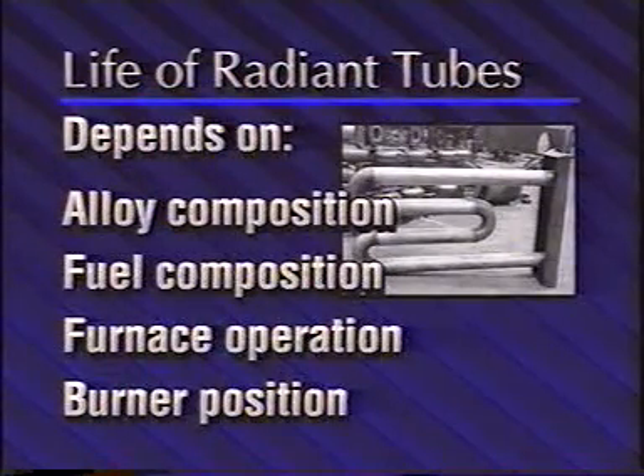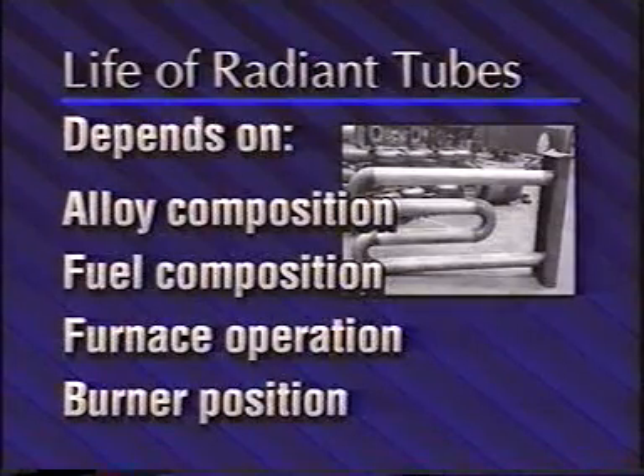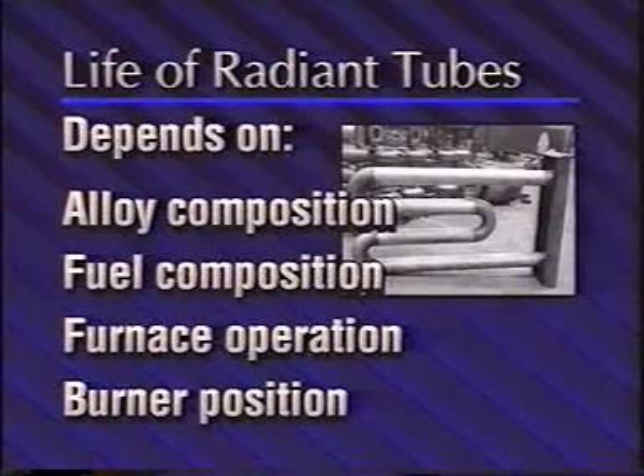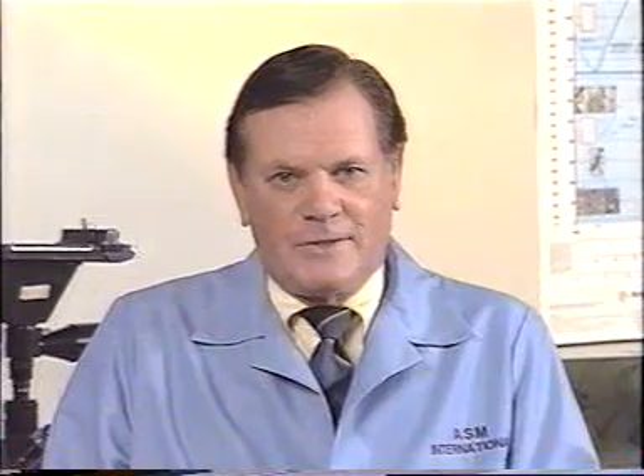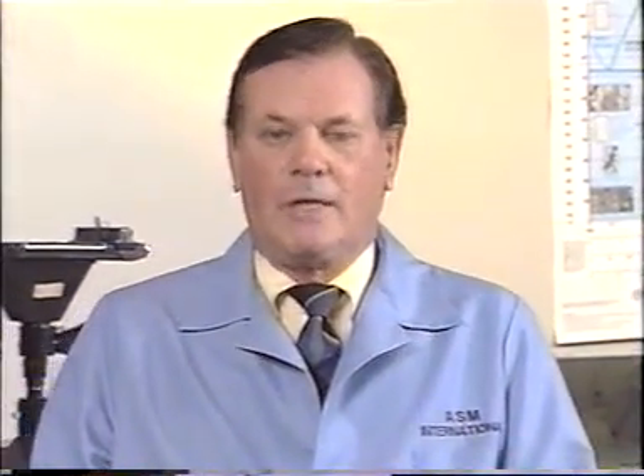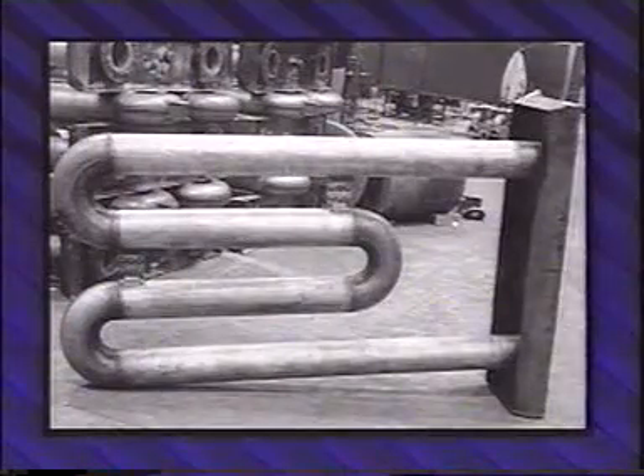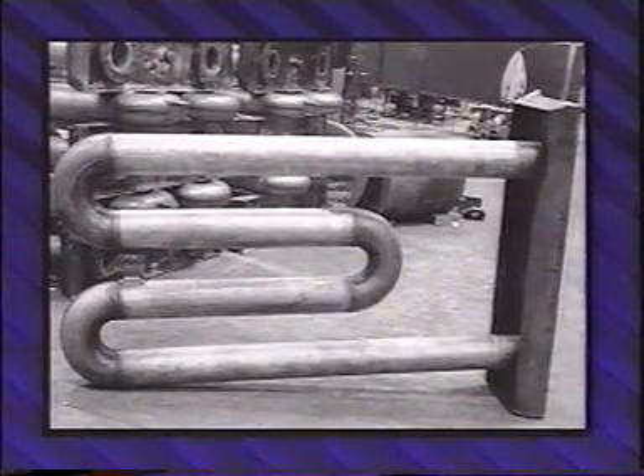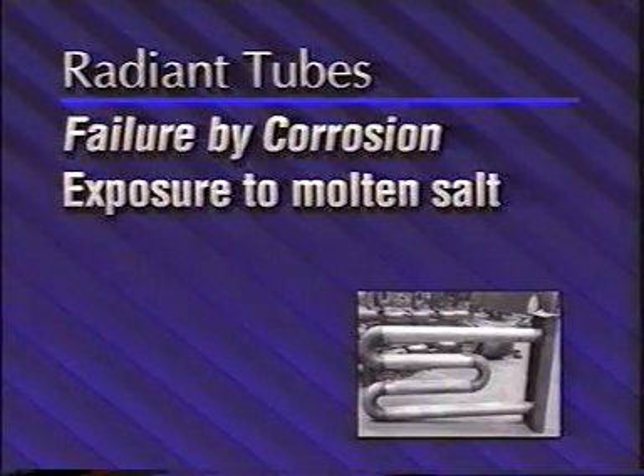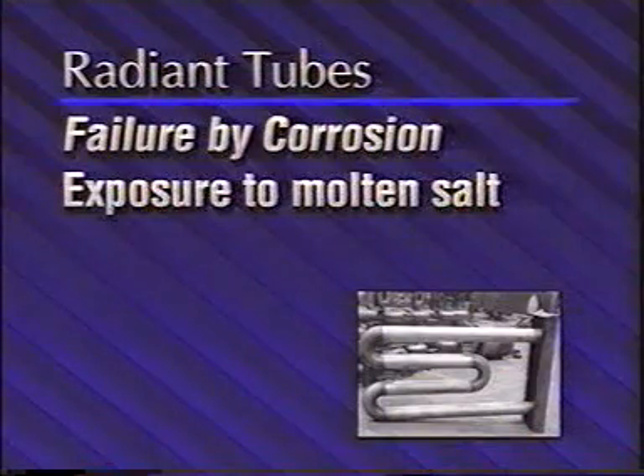One of the better proven alloys for radiant tubes in a carburizing or carbon nitriding environment is a nickel base alloy, RA 333. The life of heat-resisting alloys in contact with molten salts is usually erratic. For example, thermocouple protection tubes under similar service conditions may survive 100 immersions before replacement is necessary. And then again, they may fail after only 5 or 10 immersions. The components exposed to molten salts usually fail by perforation or by structural disintegration.